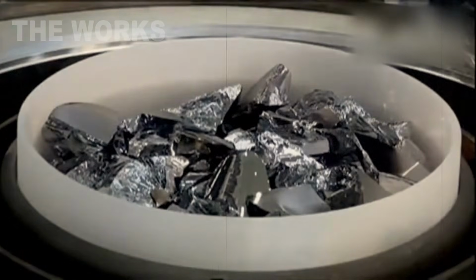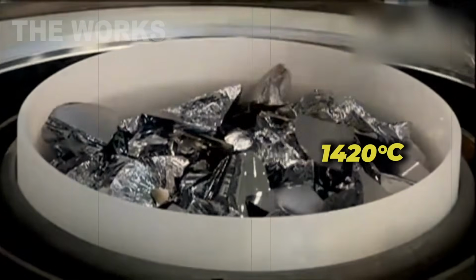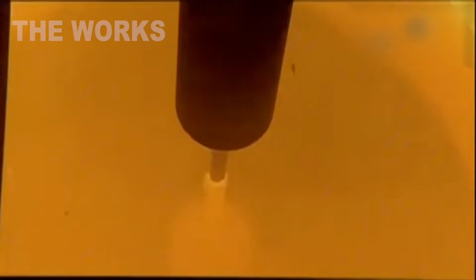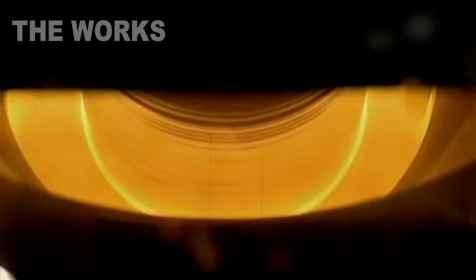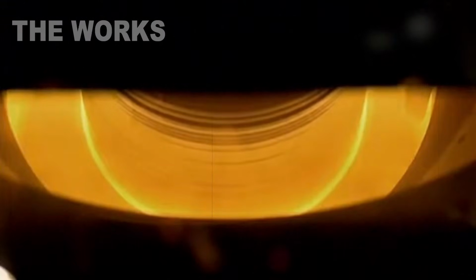Here's where an even more remarkable process begins: growing a crystal. Yeah, growing it, like a plant. Chunks of polysilicon get loaded into a quartz crucible and melted at 2592 degrees Fahrenheit, silicon's melting point. What you get is a mirror-smooth lake of molten metal. Then they slowly lower a seed crystal into the melt, a perfectly oriented piece of single crystal silicon. And they start slowly rotating it while simultaneously pulling it upward at a rate of a few millimeters per hour. The molten silicon crystallizes onto the seed, atoms locking into a perfect crystal lattice, copying the seed structure.